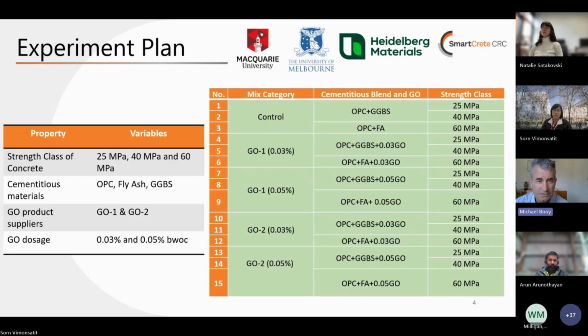Go to the next slide, please, Saun. So this was an idea of the concrete that we used for the trial program. So a mixture of 25, 40 and 60 MPa concrete. We tried it with ordinary Portland cement and slag, as well as ordinary Portland cement and fly ash. And we tried graphene oxide additive levels from 0.03 to 0.05%. So very, very low additions of graphene oxide. It doesn't take much. We used 2 different graphene oxide product suppliers. And you can go to the next slide, please, Sean.